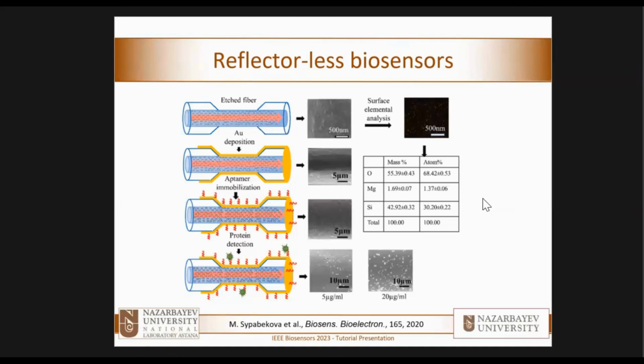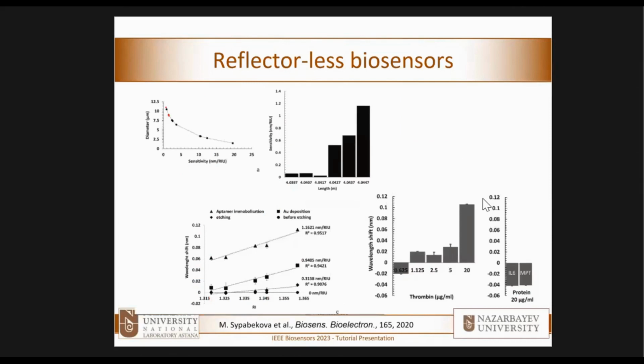Our first take was this work, where we etched a fiber and did a metallic thin film deposition, exactly the same functionalization that has been developed for the Tosi biosensor, with the same detection principle. The nanoparticles that we have developed are magnesium oxides, which is why the fiber has an excess of magnesium on the surface in the surface element analysis. By making the fiber thinner and thinner, you get better sensitivity. I'm not going to discuss this work in detail, because it's a known method. The problem is that it is quite demanding in terms of etching. You have to etch the whole cladding away. Is there a better way to do that?